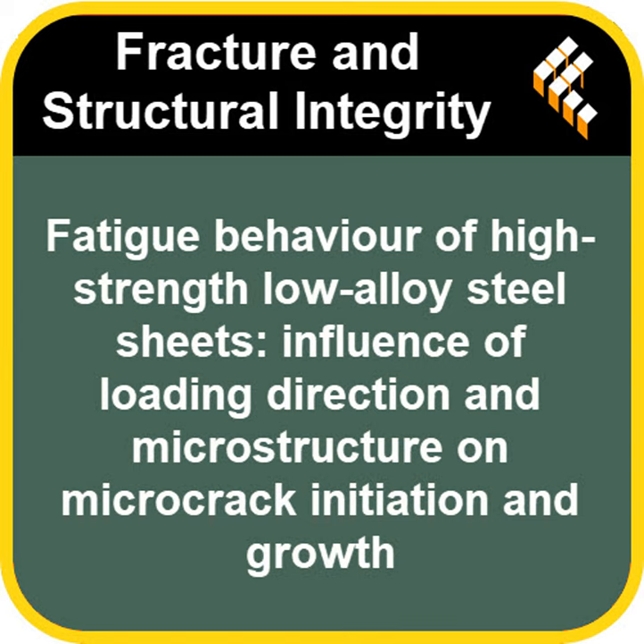They also saw tiny intergranular cracks forming between the grains, especially where ferrite met pearlite, likely due to stress building up at that interface. And interestingly, they saw some pearlite grains were elongated, which suggests that having finer pearlite might actually help the steel to deform more before breaking. Okay, so that's the static picture. But the real story for components is repeated stress, the fatigue. This is where you said it gets really interesting.